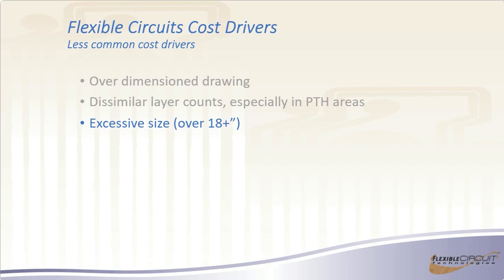Excessive size, over 18 inches. That's where you typically start seeing it bumping up. A lot of that is due to limitations of the processing equipment. A lot of the processing equipment can do long lengths, and others are not made for that. Printing machines, for instance, your printing frames are typically limited to about 2 to 3 feet in width and a couple feet in length. And so that can limit you. There are some ways that you can work around some of that stuff, but anytime you start getting longer circuits, expect that there is going to be a cost adder, and that usually kicks in between 18 and 24 inches, where you start seeing an increase in the cost.